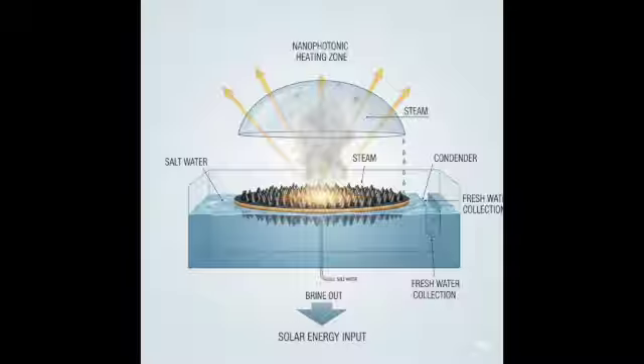Why is high porosity so important, besides just allowing vapor through? High porosity significantly reduces the conductive heat loss through the membrane structure itself. Remember, those pores are filled with air or water vapor, which are excellent insulators compared to the solid polymer. So high porosity enhances flux and thermal efficiency. So the design challenge is achieving high porosity with pores that are large enough for good flux, but small enough to maintain a high LEP, a balancing act. A critical balancing act, often managed by aiming for a narrow pore size distribution within that optimal range.